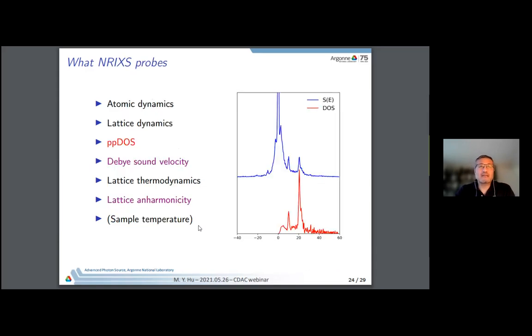And then the other technique, which involves phonons, these we can measure. So here we show the typical energy spectrum measurement. This is the phonon excitation density function, right? You see in the middle there's a huge elastic peak. That's exactly on resonance, and below and higher there's also nuclear resonance happening, and that tells you the phonon involvement, and hence the dynamics, the vibration of the nucleus, and hence the atom, right?